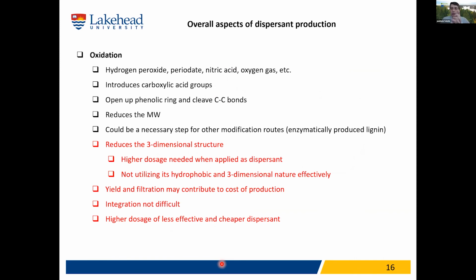So what we notice out of oxidation: we have done a lot of hydrogen peroxide, nitric acid, oxygen gas, and so many different approaches for making lignin-based dispersant out of oxidation. Usually they introduce carboxyl groups and open up the phenolic ring and C-C bonds. They reduce the molecular weight, but this could be a necessary step for other modification, if you want. But they kill the 3-dimensional structure of lignin.